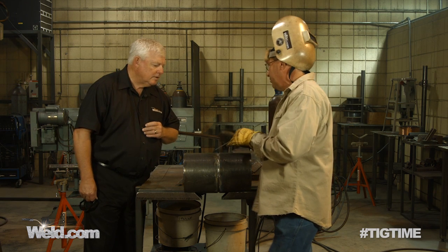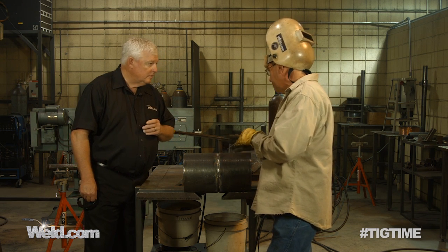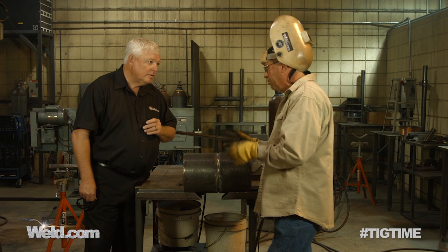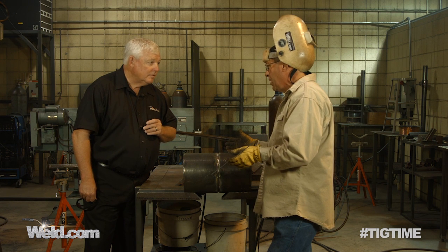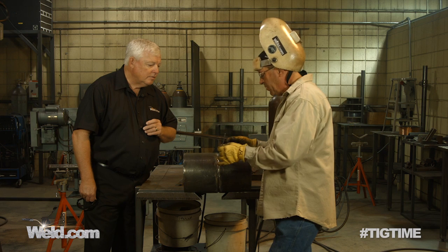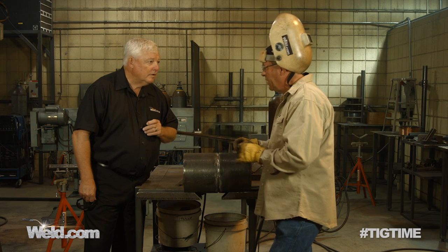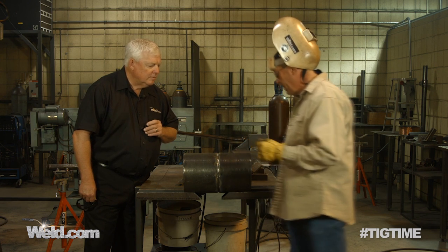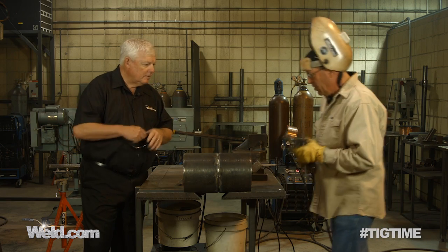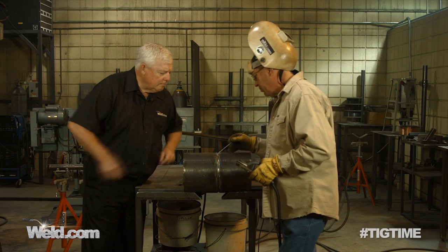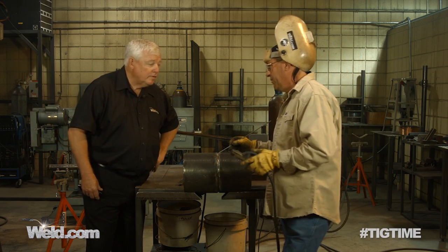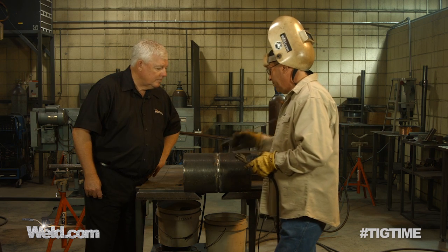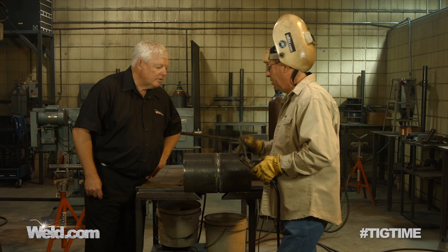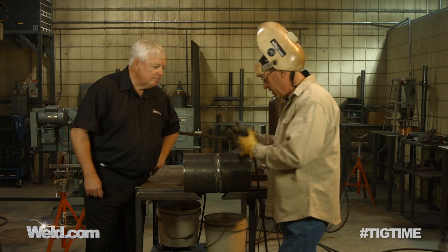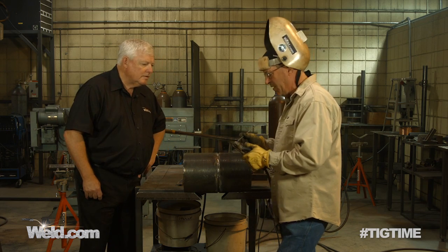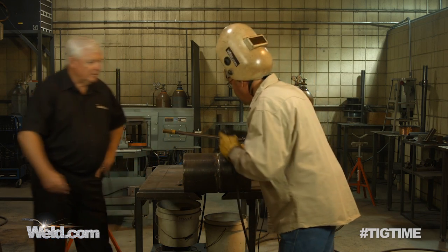The appearance of this bead that I run, I should be able to take the wire wheel and just buff it, not do any more grinding. The only grinding that I would do is on a high bump where I left my start. So I ran this root about 75, 80 amps. And now I'm up to 95, 100 amps. So this is going to run pretty hot. Again, because I want to dig that stuff out of there.